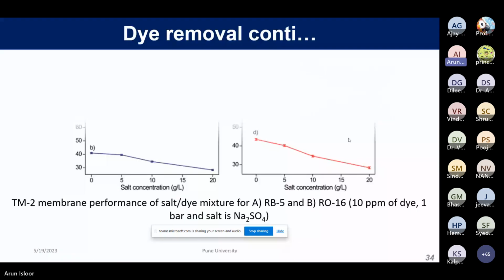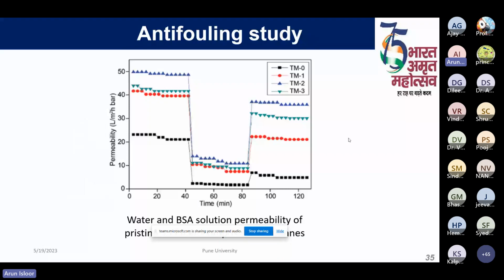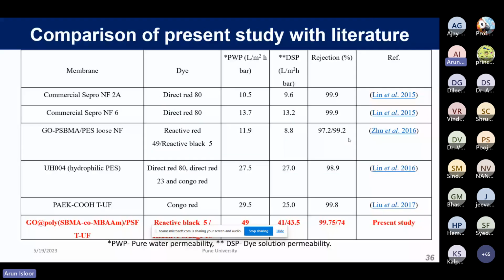Then again, the anti-fouling properties were also studied. The membranes which contain graphene oxide modified zwitterionic nanoparticles as an additive showed significantly lesser fouling. That means the added material acted as an anti-fouling material, so thereby the lifespan of the membrane is again much higher.